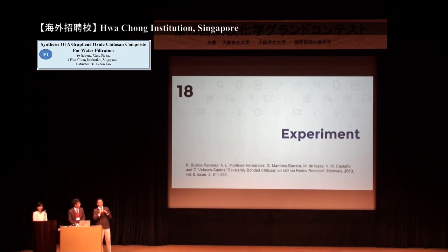Yeah, so thank you for your question. As we mentioned, we are looking at more characterization methods, because one important issue is certain things like, for example, graphene oxide. It's an oxide, so you can't carry out FTIR of graphene oxide because there's going to be a lot of OH groups, so it will mask your FTIR graph. So that's why we mentioned that we are looking at doing Raman, and of course we are also looking at doing more comparison between just the graphene oxide film and our film, which is a composite between chitosan and graphene oxide.